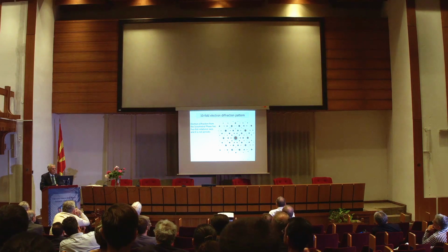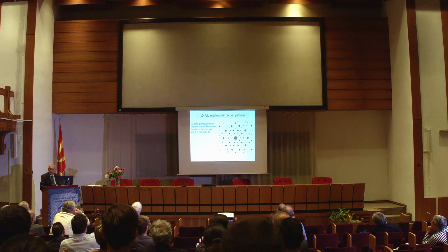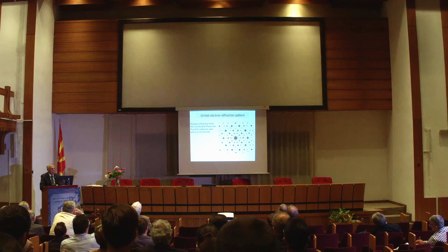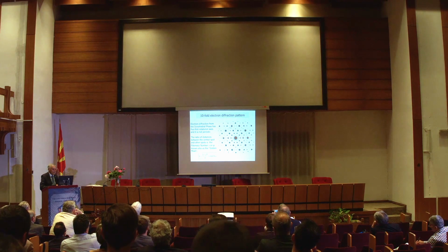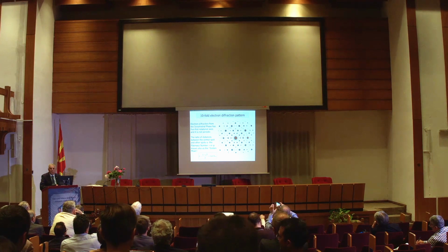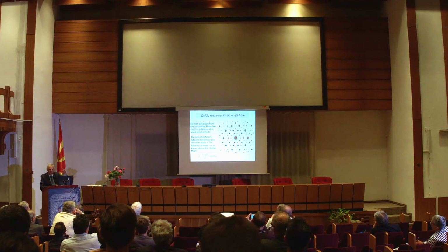And it is not periodic. You see, if you go along this line, you don't see any periodicity. The distances are not periodic. And if you take distances and divide by one another, then you get that the ratio of distances is really the Fibonacci number tau. And this is an irrational number. This is the wrong sentence to say, that if you measure A divided by B, you get an irrational number. It cannot happen. But of course, the measurement is not very precise on electron diffraction. And by theory, this is an irrational number.